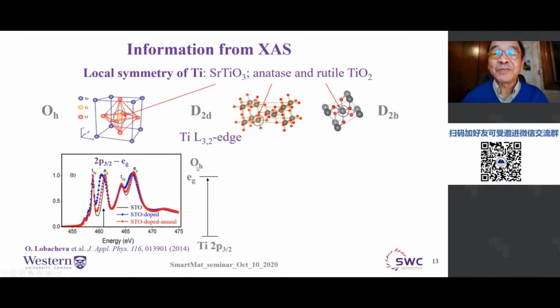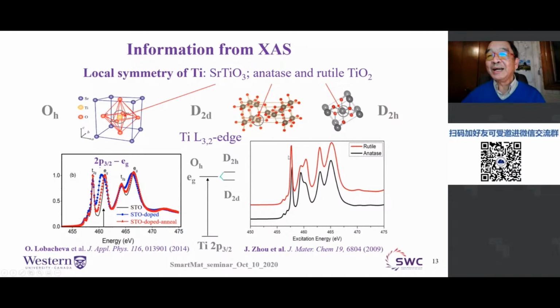Obviously, because of the octahedral crystal field, there's a degeneracy, and you see one peak. But if it's distorted, then you see two peaks. So when you look at the spectrum, you clearly see the splitting. And not only that, they have different intensities depending on the direction of the splitting. In fact, this kind of splitting can be used to identify the phase of titanium dioxide. So it's a very powerful tool. Straightforward, you don't even have to do any interpretation, and you know right away that if you see something like this, you have TiO2 in the rutile or anatase state.